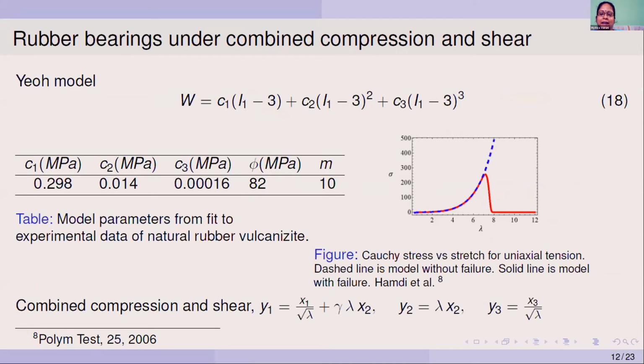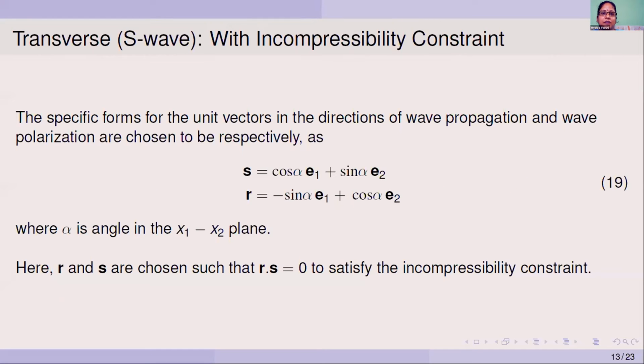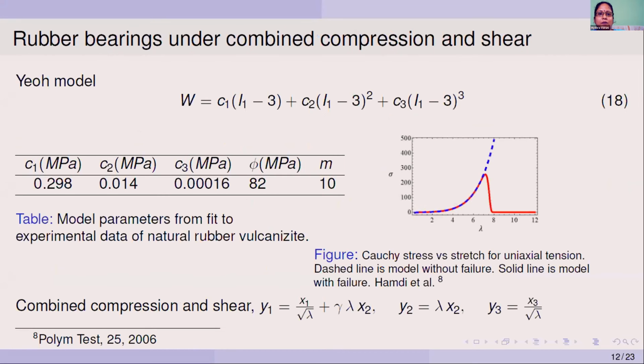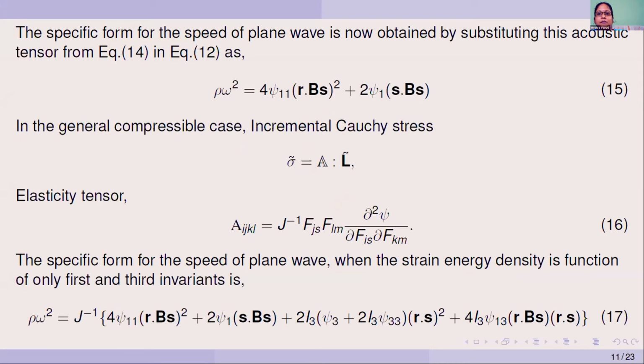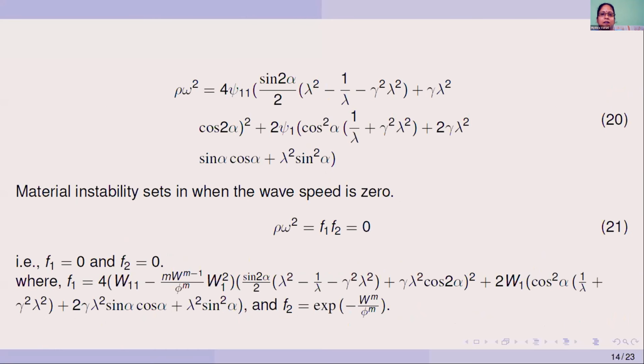So from this equation of motion, we calculate the deformation gradient F, and from it we get the left Cauchy strain tensor B. Then these are the specific forms for the unit vectors in the directions of wave propagation and wave polarization. Here alpha is the angle in the x1, x2 plane, and this particular form is chosen for these unit vectors such that the incompressibility condition r dot s equal to 0 is satisfied. Now we plug in these specific forms of R and S and the calculated left Cauchy strain tensor B into this equation for the wave speed in an incompressible material, and we obtain this equation number 20.